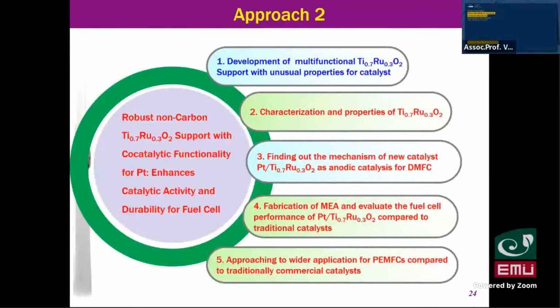So in this approach, we introduce a second method: doping ruthenium oxide into titanium oxide, with a ratio around 0.3 ruthenium to titanium oxide. Ruthenium has interesting properties that can enhance this material for anodes. So we carried out this study from synthesis, characterization, finding the mechanism, and fabrication.